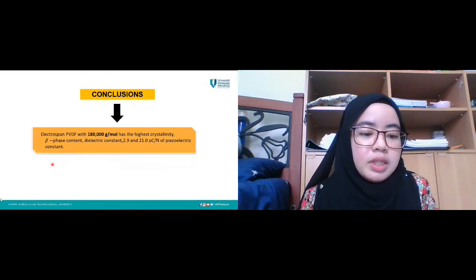In conclusion, the high content of beta phase in the lowest molecular weight, which is 180,000 grams per mole, results in high dielectric constant and piezoelectric constant. And it is the ideal molecular weight to produce a good piezoelectric constant.